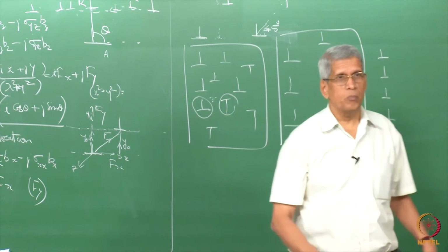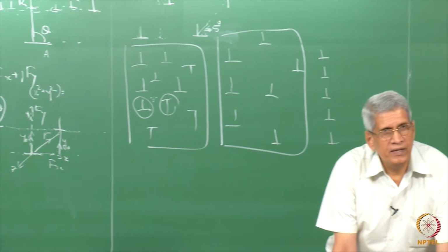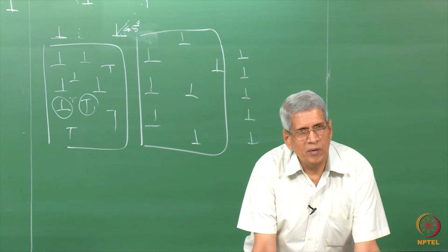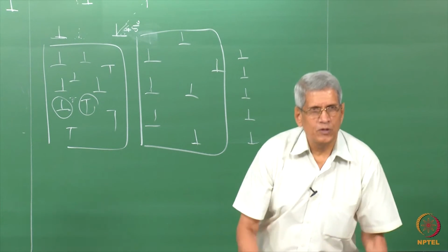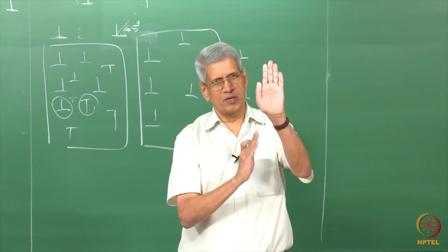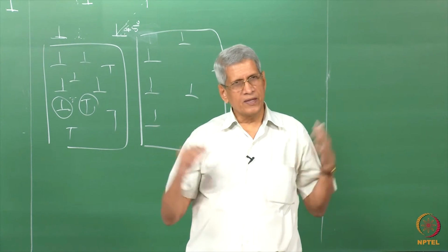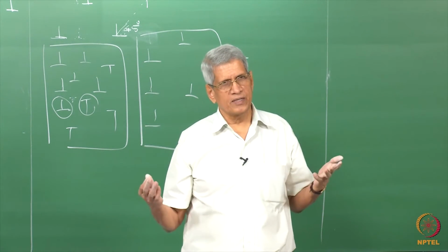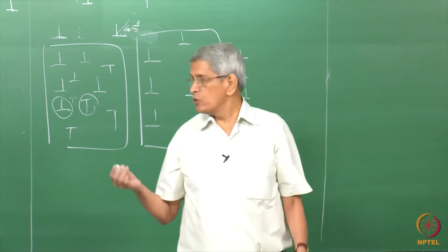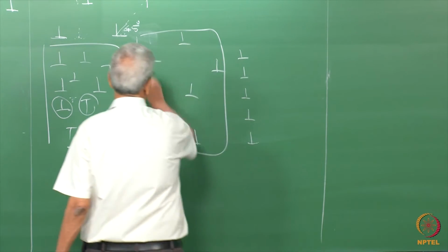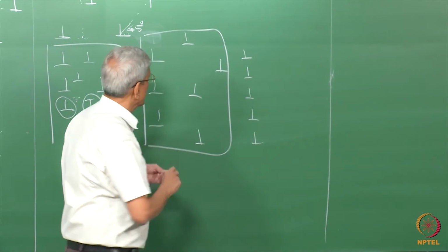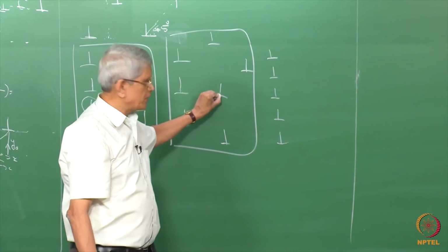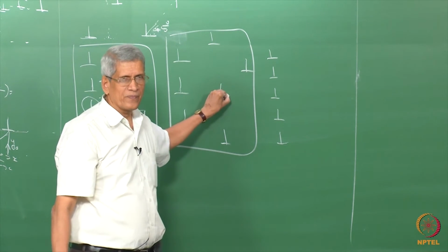This we call a polygonization phenomenon, correct? You might have studied what polygonization is. That is, dislocations move and arrange themselves one on top of the other. Essentially, this creates what we call a small angle boundary. So, if the dislocations are randomly distributed, the forces between the dislocations are going to be high.